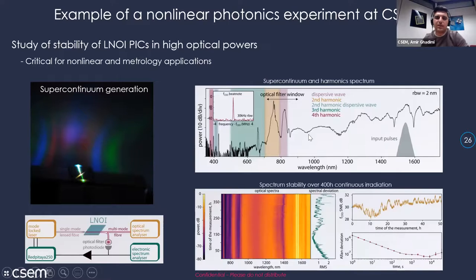One of the big concerns we had was the stability of lithium niobate, because lithium niobate is known to start to see damage in the crystal under high power radiation. So we let this experiment run for 400 hours, and you see the accumulated spectrum over 400 hours. Looking at the spectral deviation and the Allan deviation of our beat note shows that this experiment is very, very stable. The experiment wasn't temperature stabilized, so it was just free running. We think that this extra drift is coming from misalignment of the fiber and the chip at the beginning.